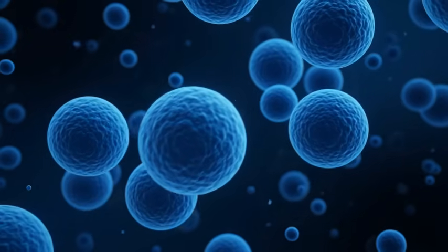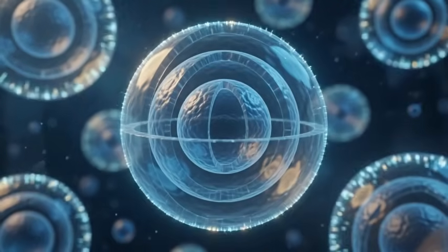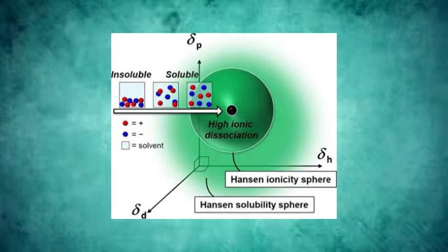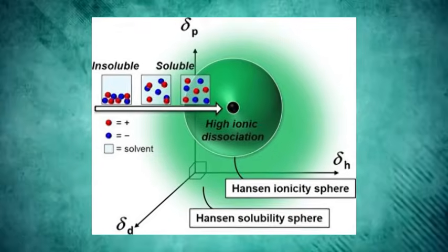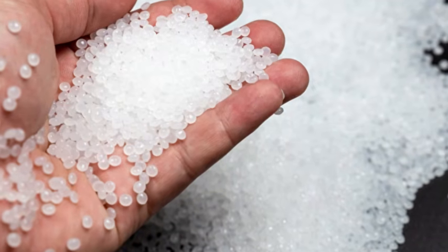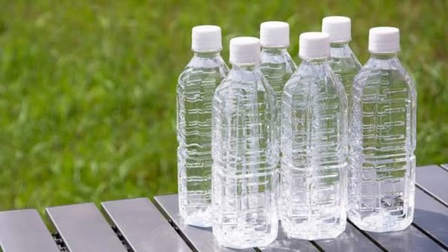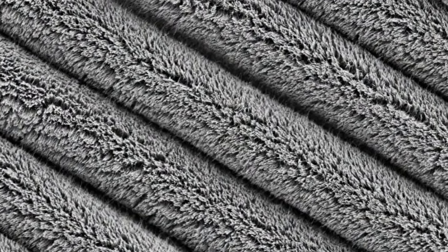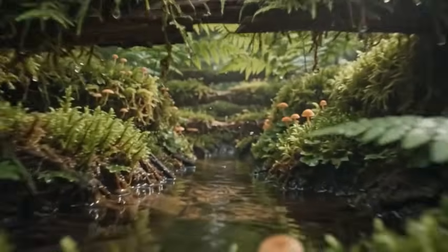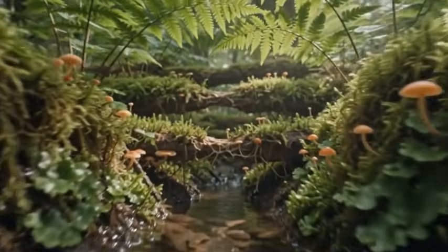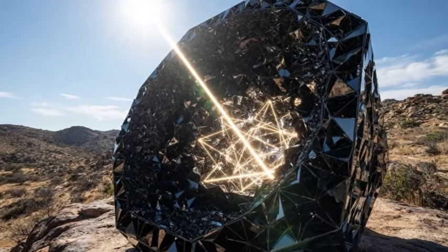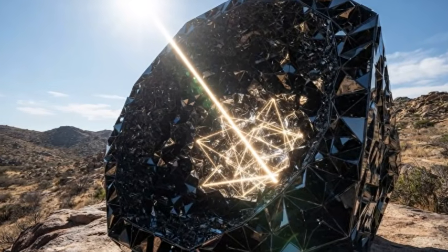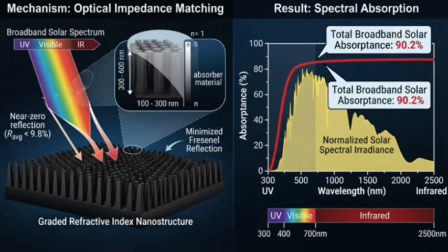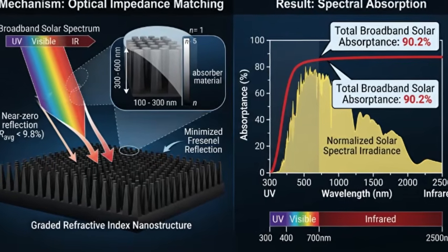Instead of solid nanoparticles, they built hollow, multi-layered nanospheres, and then used something called Hansen's solubility parameter theory to precisely thread polyethylene terephthalate polymer chains, the same plastic family as a water bottle, directly through the pores of those hollow shells. Once locked in place, the structure forms what the researchers call a nanoforest. Picture dense, layered undergrowth instead of a flat surface, with open channels running between the layers. Sunlight enters that structure and bounces around inside it instead of reflecting away, which is how the material ends up absorbing 90.2% of the broadband solar spectrum.